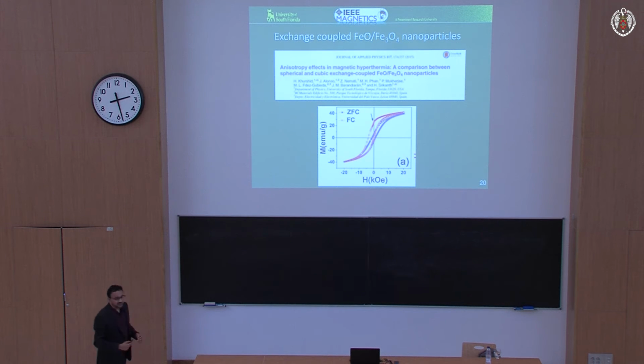Okay? This is also a spin valve. Here's our measurement showing you exchange bias. We can actually shift the loop and all that you expect. But in this case, we are convinced that this is the right system because we have magnetite completely encapsulating the FeO. We don't have Kirkendall effect. It's a stable system, so we thought this is the right thing.